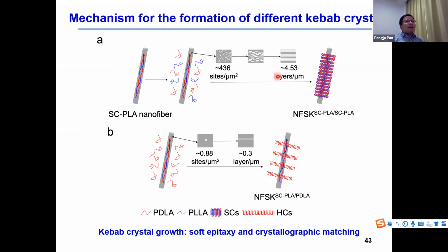When the stereocomplex fiber was immersed in the PLLA and PDLA mixed solution, both the kebab and the shish are stereocomplex crystal, and they have good crystallographic matching. So there are many nucleation sites. This leads to growth of more kebab crystals. However, when the stereocomplex fiber was immersed in the PLLA or the PDLA homopolymer solution, there are few nucleation sites. This induces the growth of few kebab crystals.